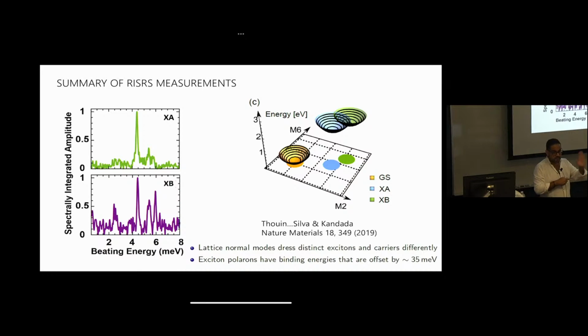Now we go resonantly with XB, and now we see that these relative intensities are very different. Now we still have this M2, but now these guys are very important in the dressing of the exciton B, as well as these. Okay, so now we take these amplitudes, the relative amplitudes, and we plot. This is just a Mathematica sketch, but the energies and the relative displacement here come from the measurements.